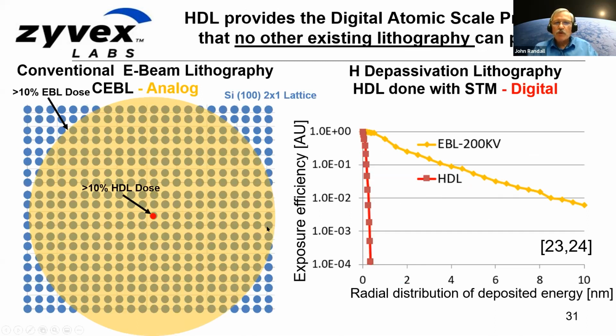I don't have time to go into the reason why this point spread function pushes an exposure zone for E-beam lithography out to about 4 nanometer radius, and produces a lot of partial exposure. Versus hydrogen depassivation lithography, because of a couple of nonlinear functions, produces an extremely small exposure zone, which lets people like Lyding and Walkup pop off individual hydrogen atoms.